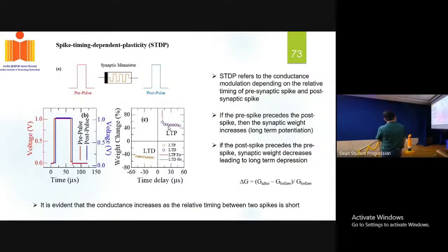And we also tried to see spike-timing-dependent plasticity by applying a presynaptic pulse and a postsynaptic pulse to the synaptic memory device. And we do see an increase in the weight change as we decrease the time between the presynaptic pulse and the postsynaptic pulse. So this proves that long-term potentiation, long-term depression, and spike-timing-dependent plasticity are the basic operations of our brain, and the graphene oxide based device is also mimicking a brain. So from this we can confirm that our graphene oxide based device is mimicking the brain functionality.